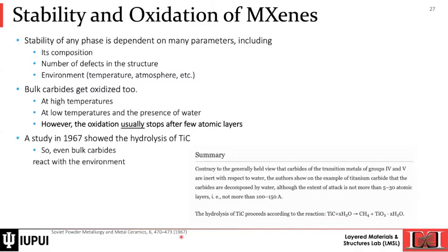Also, they are stable at high temperatures, but we know at high temperatures, every material, if they're stable, will have a protective oxide scale around them. So everything will get oxidized. Now the oxidation depth becomes extremely important when we work with a material that is only a few atomic layers. So that's why MXene oxidation becomes a major issue, and also it creates the best platform to study stability of carbides.